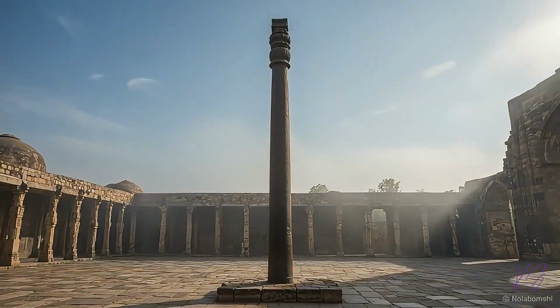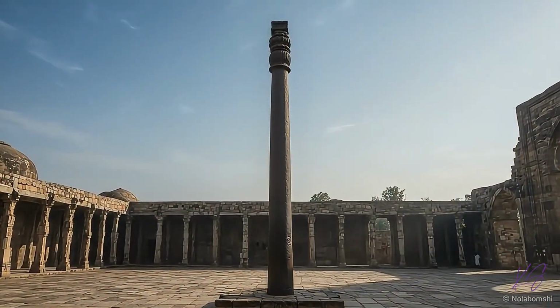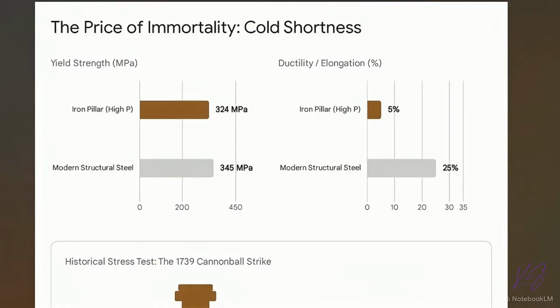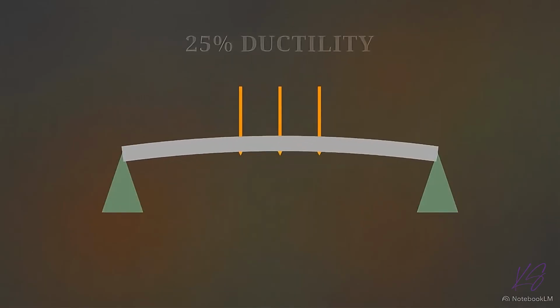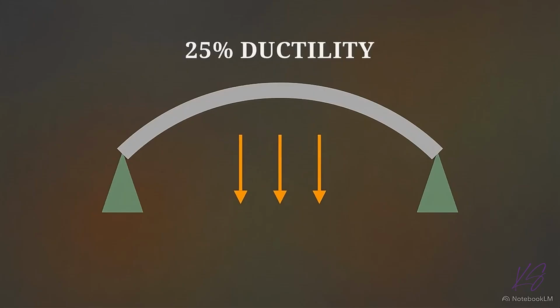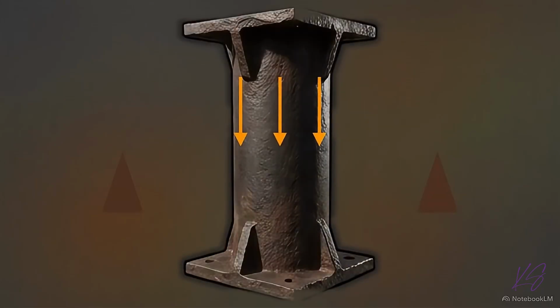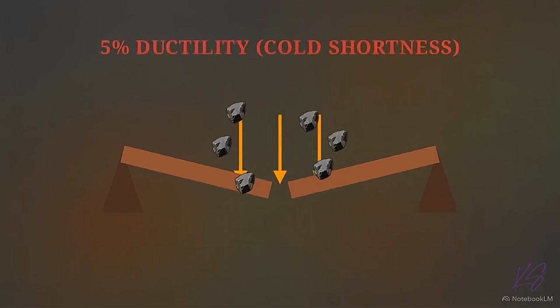This chart highlights the mechanical penalty of high phosphorus iron. The alloy suffers from a defect called cold shortness, leaving it brittle with a ductility of only 5%. Modern structural steel stretches up to 25% to absorb stress. If you attempted to build a modern bridge with the pillar's alloy, the supports would snap under tension.